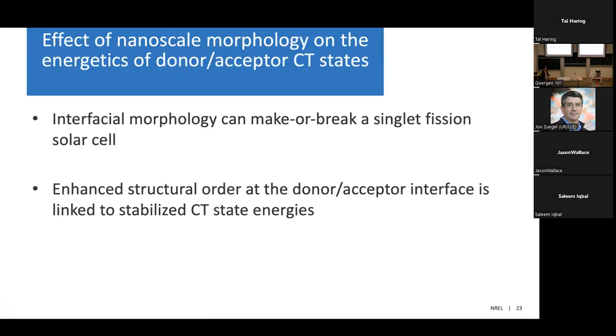Okay, so that concludes the first section of my talk on the effect of nanoscale morphology on the energetics of donor-acceptor CT states. And the two key takeaways are that essentially the interface morphology in these devices can make or break your singlet fission solar cells, and that having enhanced structural order at the interface is linked to lower charge transfer state energies.